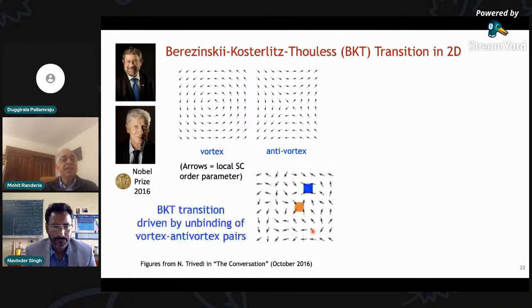And what Kosterlitz and Thouless said is that the Kosterlitz-Thouless phase transition, of going from a superconducting state with an algebraic order, a sort of long-range order in these phases, to a completely phase-disordered state, which therefore has no superfluid density, no superconducting properties, is through the unbinding of vortex-anti-vortex pairs. That is the content of their Nobel Prize. Okay, so inside the superconducting state, vortex-anti-vortex pairs are strongly bound, and as a result, basically long-range or algebraic order technically persists.